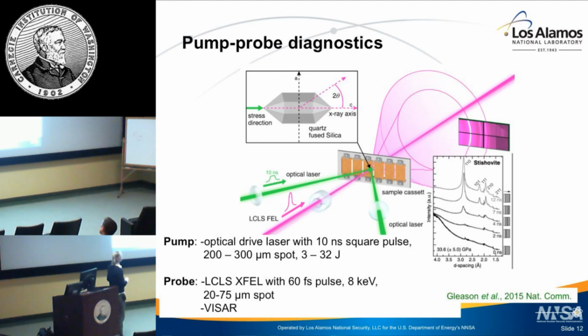We send in our X-ray probe, shown here in pink, and in some of our experiments we orient the starting material in a particular way so we can track changes in texture, preferred orientation, or fabric as a function of shock compression. Downstream we have area detectors. This is going to collect the Bragg peaks, or the 2D slice through the Debye-Scherrer cones, so that we can then integrate and identify what is the resultant high pressure phase.